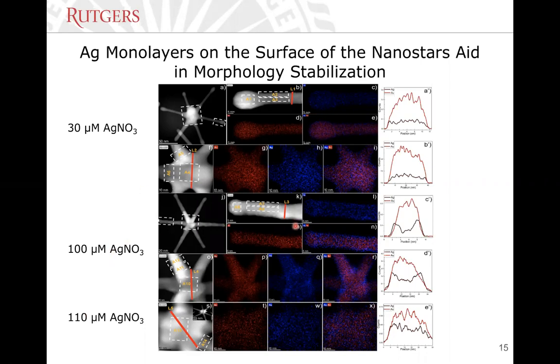So there is a lot more to understand, but this is very interesting because it does confirm that silver is not an irrelevant component of this nanoparticle, and confirms some of our previous results that we collected with ICP studies, where we had identified a huge concentration of silver in these particles, and we didn't know why. So now we finally know where it ends up going.